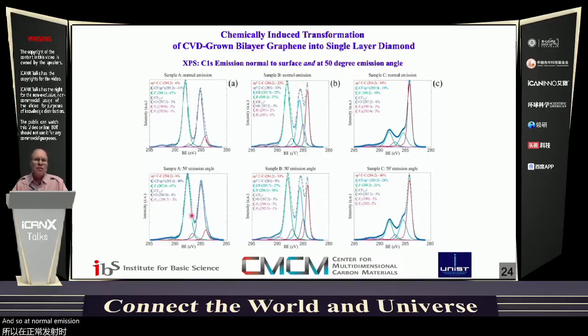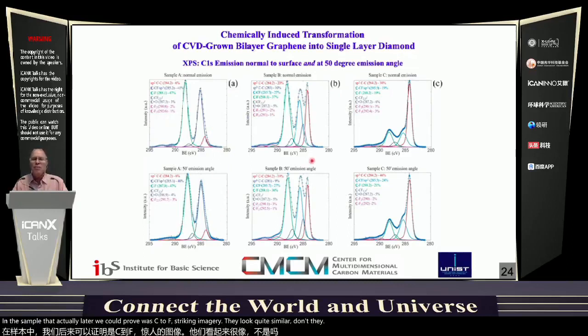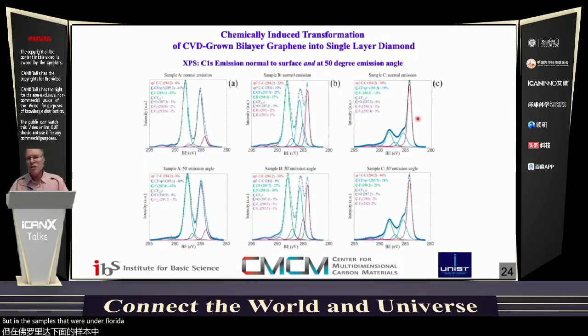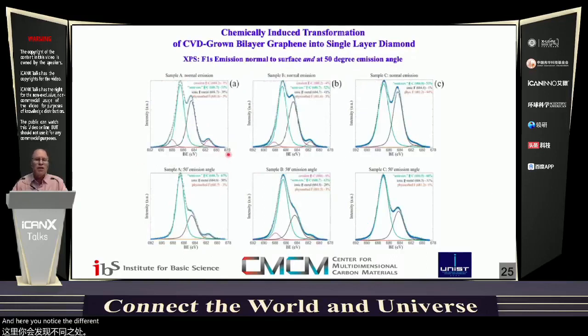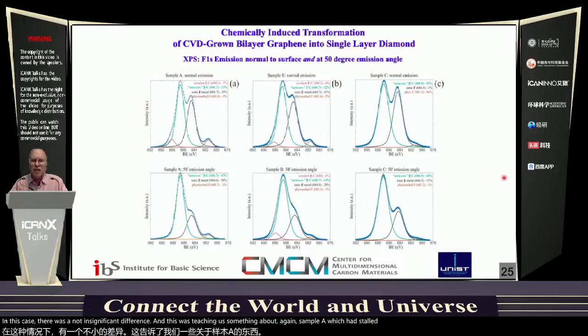And so at normal emission and at 50 degree emission, in the sample that actually later we could prove was C2F stoichiometry, they look quite similar, don't they? But in the samples that were under-fluorinated, insufficiently fluorinated to reach C2F, they still have some, one can say, graphene-like character. There was a strong difference between the normal emission and the 50 degree emission angle. And here you notice the different energy. We're now in the F1S, and we could do the same thing, emission normal and at 50 degree angle. And this was, again, very valuable because in this case, there was a not insignificant difference. And this was teaching us something about, again, sample A, which had stoichiometry C2F.